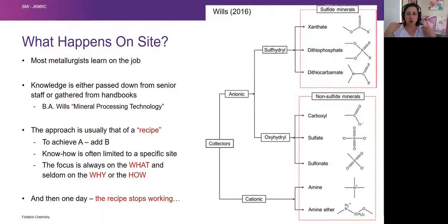Can we use the same reagents when treating slimes, even though there is enough valuable mineral, or should we change the ratio or composition? Slimes are never quite the same as large particles, even if it's the same ore ground down to that size, because the composition and liberation of individual particles changes. You would need some modification. Unless your system mineralogy is such that the individual surface composition of particles doesn't change as a function of size — which it always will — you will have to make modifications to the type or quantity of reagents you're using.